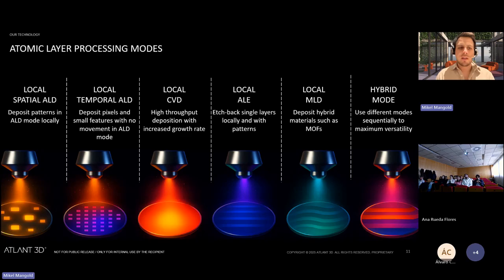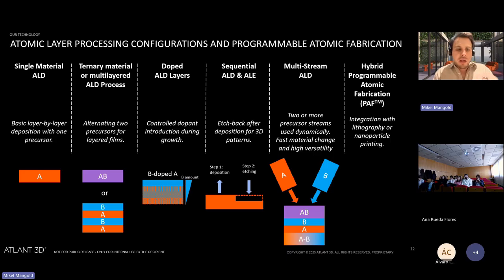So this is not just, again, what I said before. That has all the different opportunities, the way we can deposit. We can do etching and molecular layer deposition, or even a mixture of both. So we can do deposition and then right after a cleaning or etching step. You can see in the example of ALE and ALD here in the middle, we can deposit, and then if we want to do a little trench, we can switch it to ALE mode and make a trench. As you know, before, to do that, you had to fully coat the wafer, and then put it in another machine for the etching step. We can do it right away.